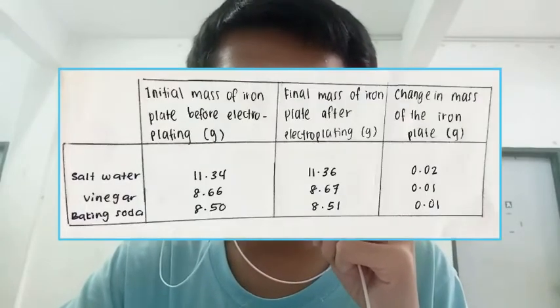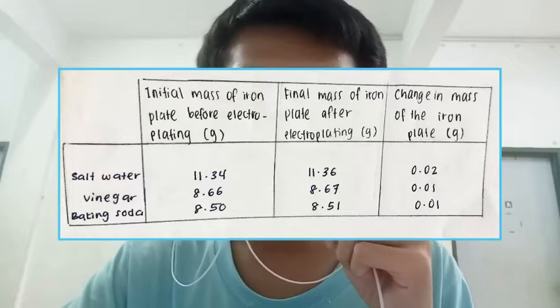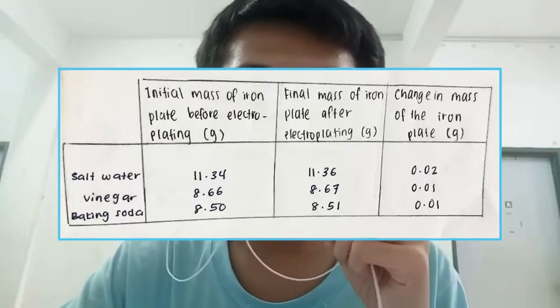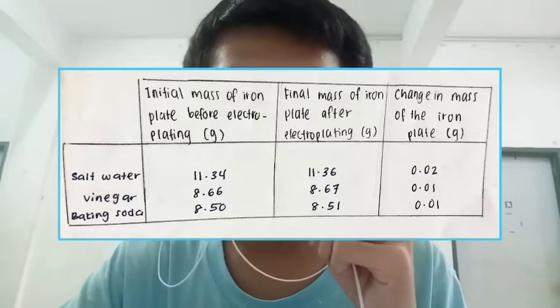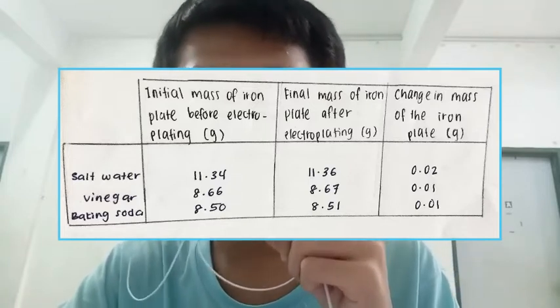So after we obtain the value of the mass of iron plate before immersed in electrolyte and the mass of iron plate after immersed in electrolyte, we calculate that the change in mass of iron plate in each of the electrolysis are 0.02 gram, 0.01 gram, and 0.01 gram respectively. The duration of electroplating process in all the experiments are 30 minutes and the current flow through the electrolyte in all the experiments are 2.5 milliamps per second.